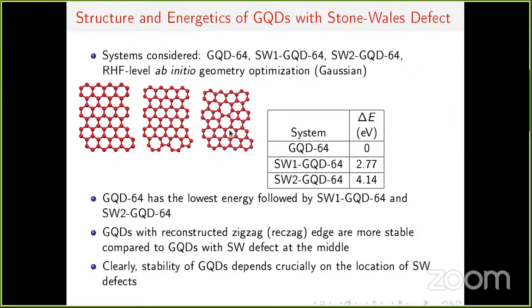First we did the geometry optimization of these three quantum dots to obtain the correct bond lengths to be used in our calculations. Quite expectedly, we found that the lowest energy quantum dot was the pristine one. Then SW1, with the Stone-Wales defect at the edge, is 2.77 eV higher than the pristine one, and SW2, with the Stone-Wales defect in the middle, is 4.14 eV higher. I have already mentioned what is written in the points here, so let me move on to the next slide.